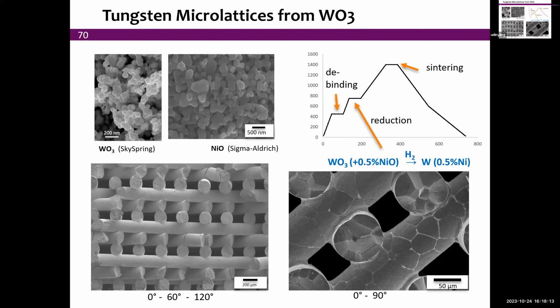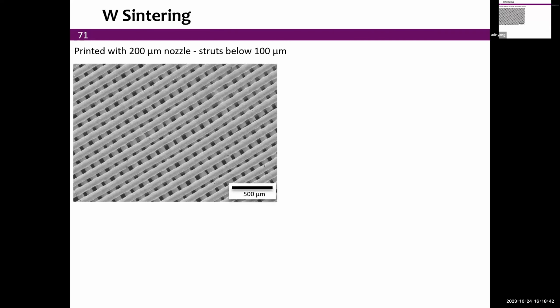This is now fully sintered tungsten at a temperature which in that case is about 1300 degrees C, which is really low temperature for tungsten. I mean, tungsten normally with that nickel would need easily 2000 plus for sintering. The nickel effect was known, but on particles of pre-reduced tungsten, not so much on nascent tungsten from reduction of tungsten oxide. So we are pretty pleased with it.